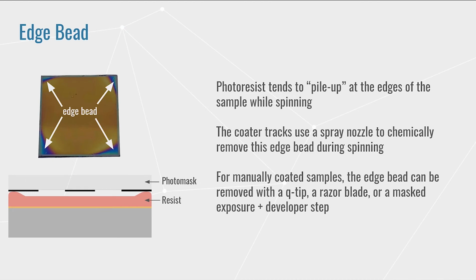During the spin coat step, an edge bead forms as photoresist piles up on the edge of the sample. If the sample is then placed in contact with a mask, there will be a gap between the critical area on the sample and mask. This gap can make the features appear out of focus when printed on the sample.